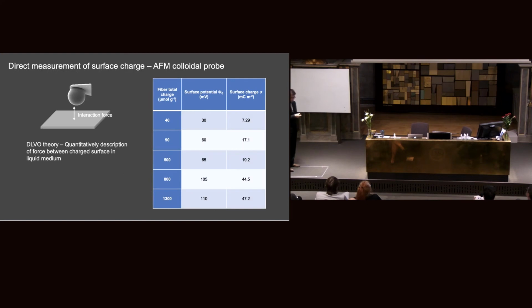Since there's a lot of process in this surface preparation, we need to make sure that after the surface treatment, this charge gradient still stays the same. Therefore, we use the AFM colloidal probe, which is a way to measure the interaction force between the surface and the probe.